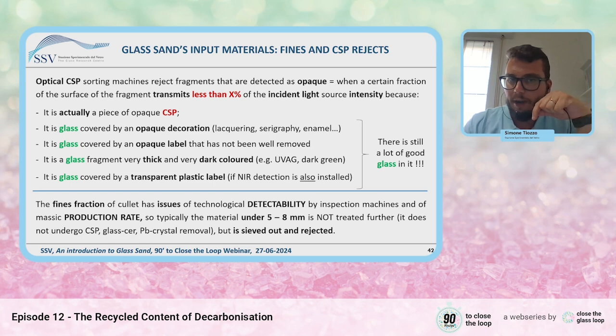rejects? Because the fines are mostly made of glass, and they can constitute a relevant part of the incoming raw cullet, because in certain places the collection is not made, for example, with big bottle banks, but can be done with compactor trucks that can crush a lot of bottles. On the contrary, the material rejected by machines that reject opaque fragments, interpreted as ceramic fragments, sometimes has false positives, because sometimes labels remain attached on the glass fragments and they are seen as opaque. Sometimes there is very thick, very dark glass, like in some champagne bottles, that is interpreted as opaque, and so as ceramic.